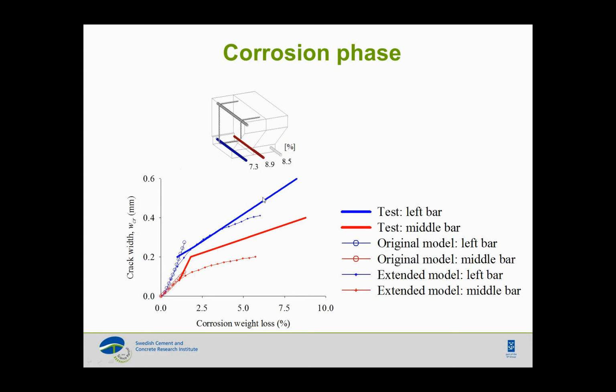And looking at the experimental results, this is how the crack widths develop for different amounts of corrosion. Of course, we have a point here at 0, and then we jump over here and continue. And if we look at the findings of the model before we include the flow of rust, this is what we get. We estimate the crack widths well in the beginning, but then we continue with quite a straight line because we do not allow for the rust to flow out in the analysis.